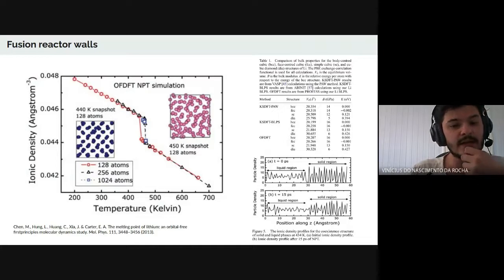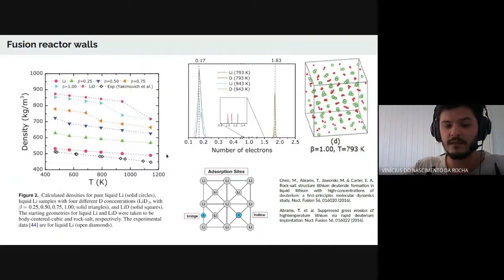DFT and molecular dynamics is a powerful tool to simulate interactions between liquid metal and first walls, and we can predict relevant macroscopic properties of liquid lithium, such as melting point, structure factor, viscosity, diffusivity, and surface tension. The nucleation sequesters deuterium in liquid lithium, explaining the observed anomalously low liquid lithium sputtering. This property could stabilize the reactor first walls beyond the capability of pure liquid lithium, which otherwise may evaporate from metal substrates at these temperatures.